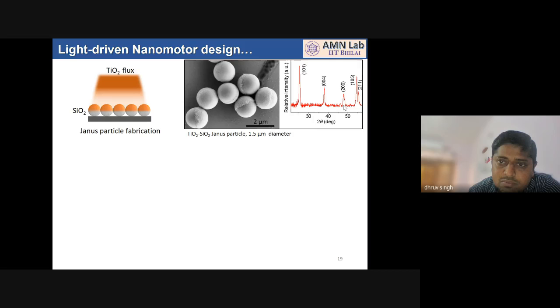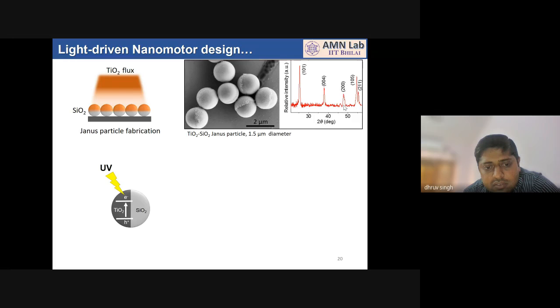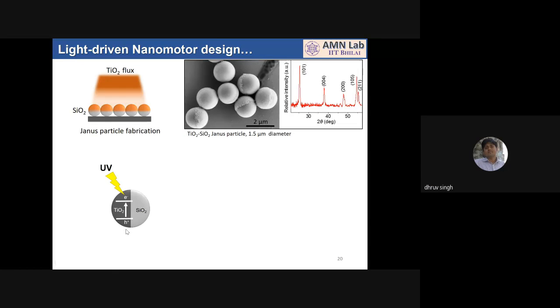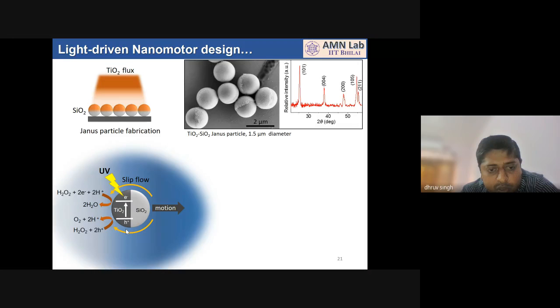So once you have a Janus particle with half TiO2 coating and you illuminate it with UV light of wavelength less than 380 nanometer, because 380 nanometer corresponds to the band gap of TiO2, it generates a pair of electron and hole across its band gap. Now, if you put it in a peroxide medium, which is very easy to decompose, these electrons and holes participate in two reactions to decompose the peroxide.